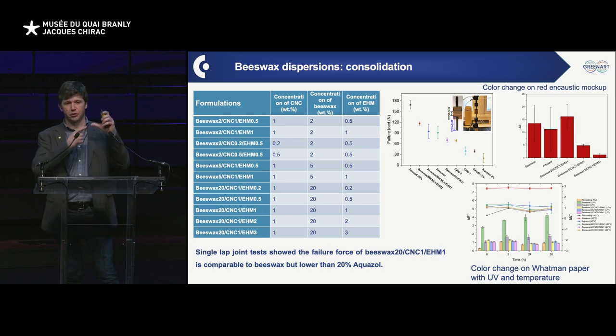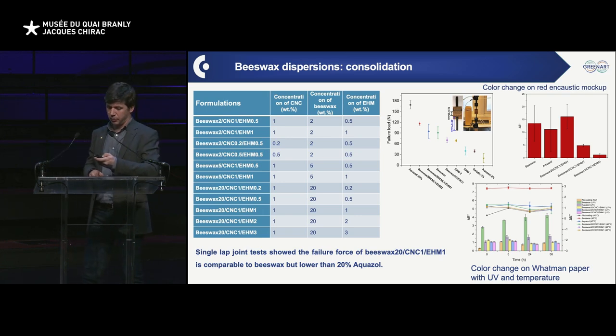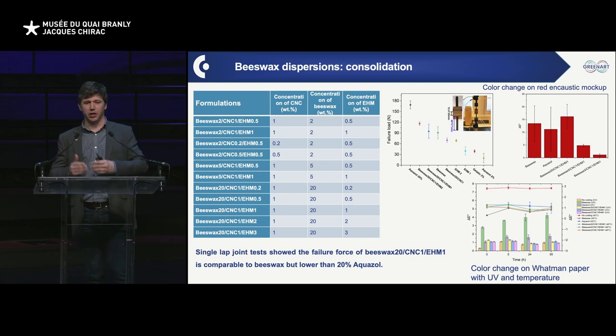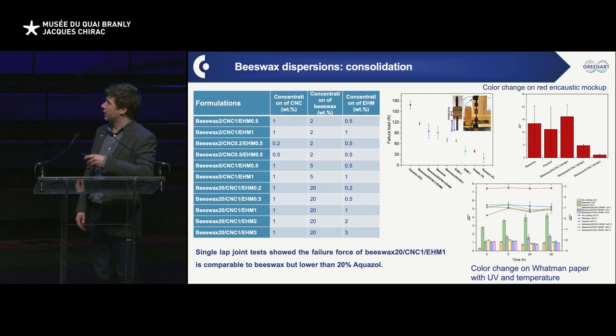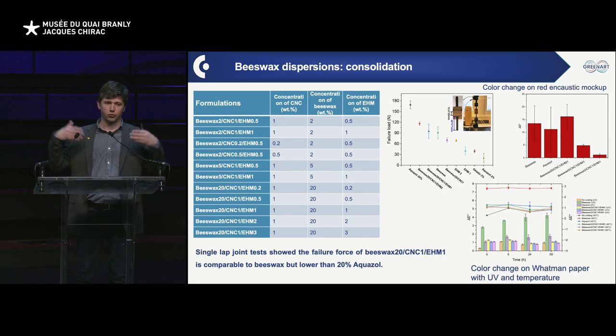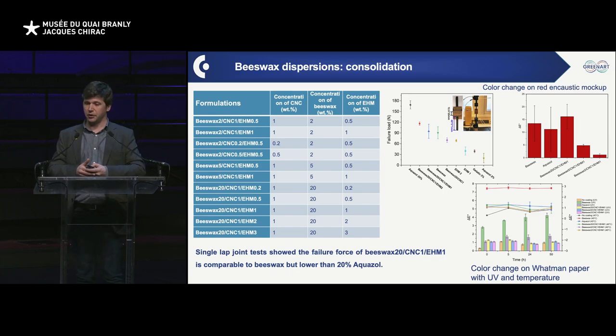So far the system was, okay, it's gluing, it's not affecting too much the appearance, and at the same time, let's see how well it will age, because it will be exposed to light, it will be exposed to temperature variation. So what we did here was to look simply at the appearance, and we aged the paper. We took Whatman paper, we coated it with the emulsion, and we exposed it to UV and temperature. So essentially the bars are for the UV, and the temperature is the symbols over here. And we can see that as a function of time, the system is barely getting modified, and essentially there is no major modification in terms of appearance, which was positive. That means we have a stable system against exposure to environmental stresses, so to say.